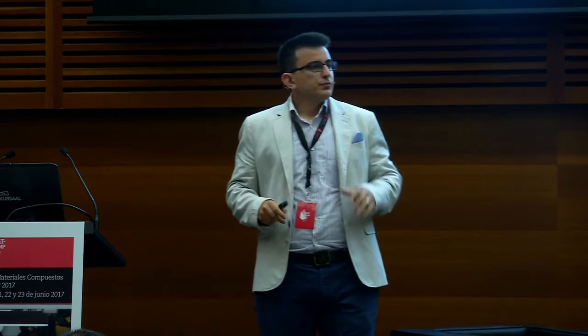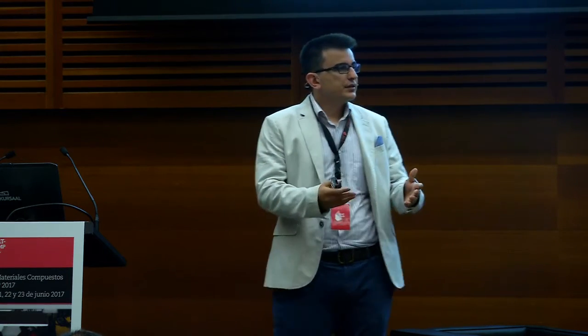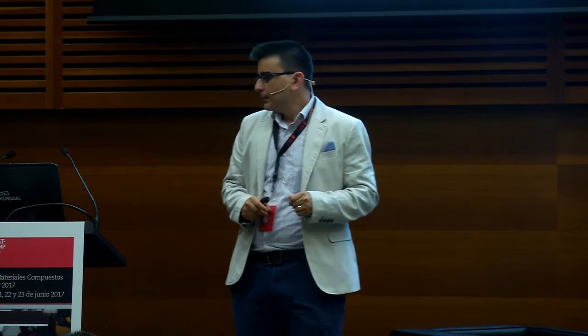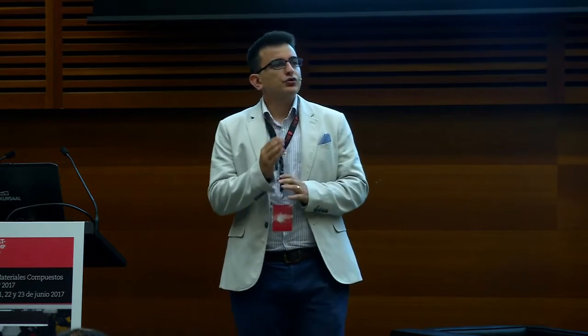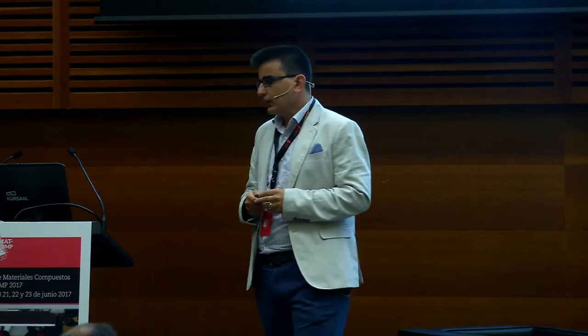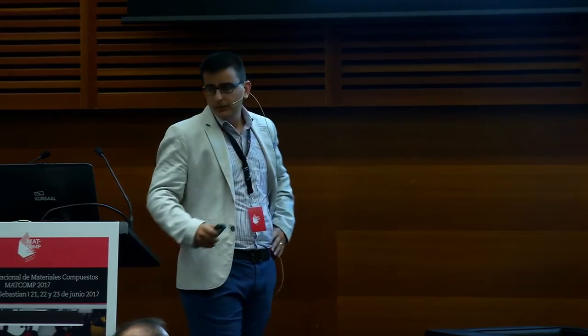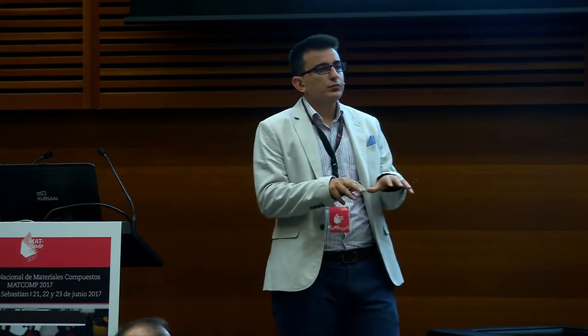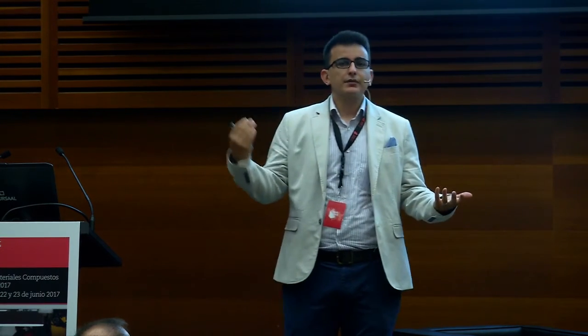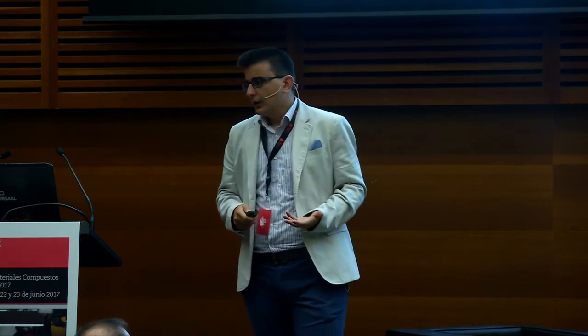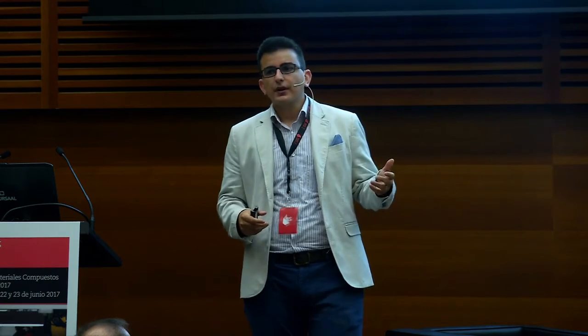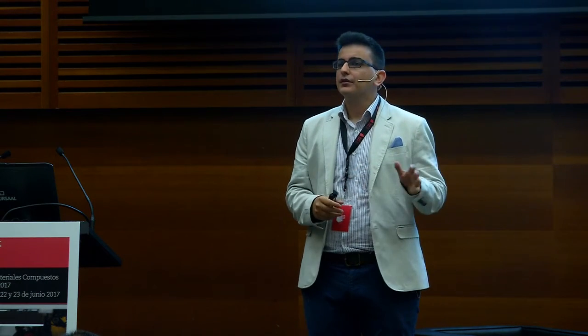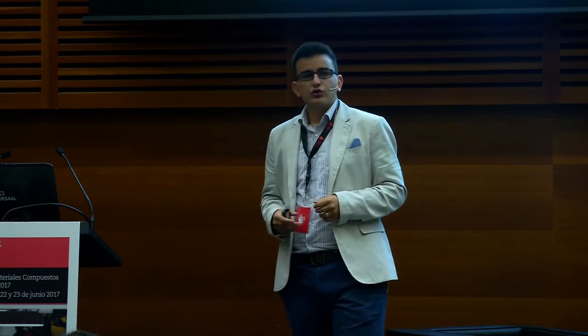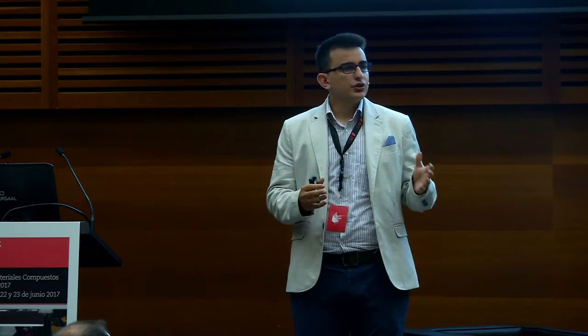I have some examples for pultrusion processes. So in pultrusion, we have discussed that we would like to maximize the pulling speed, minimize the through-thickness cure gradients, and of course minimize the energy consumption. So in an optimization problem for pultrusion processes, we can define maximizing the pulling speed and minimizing the total energy consumption. And next to it, we can define several constraints. For instance, the maximum composite temperature during the process cannot exceed 240 degrees C for degradation. And we can set a constraint on the degree of cure at the die exit, such that it should be at least 0.9, 90% cured at the die exit.